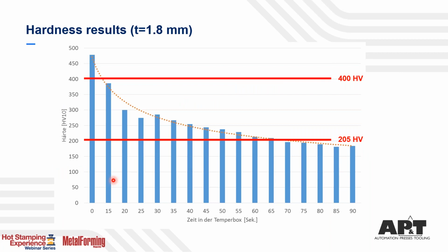Coming back to process monitoring, an important topic here is the time in the temper box and also the temperature levels that you reach after or inside the temper box. What I wanted to show you here is, on a 1.8 millimeter thick blank, how the time in the temper box affects the final mechanical properties in your soft zone. So if you have the blank too short in your temper box, you will not reach the lower end or the upper end of the soft zone. If you have it too long in the furnace, you basically reach the properties of the soft zone, but maybe you lose in cycle time.